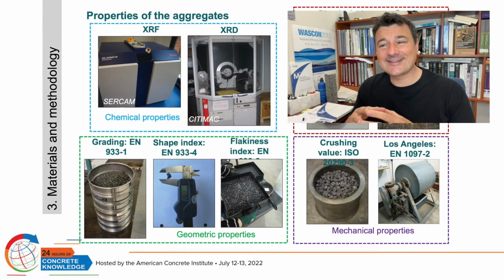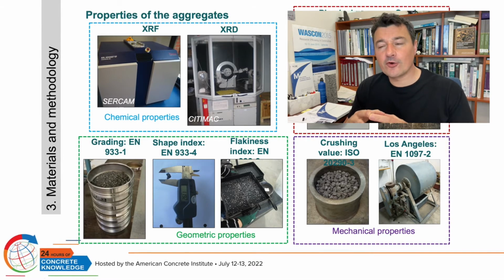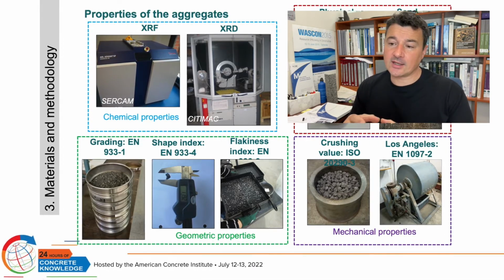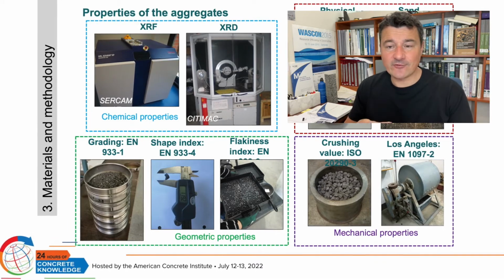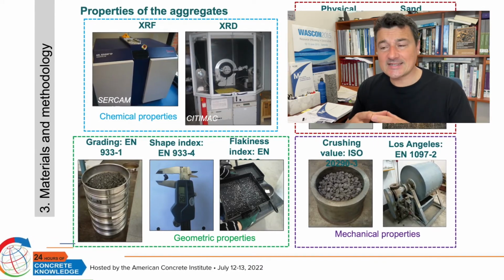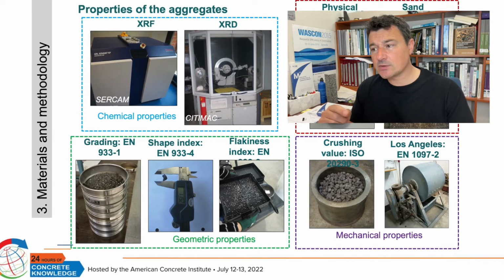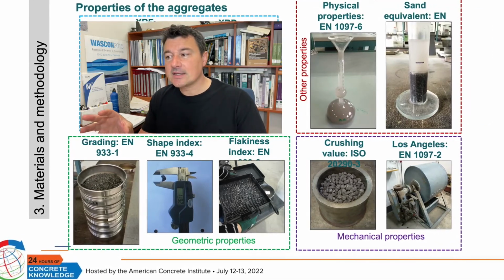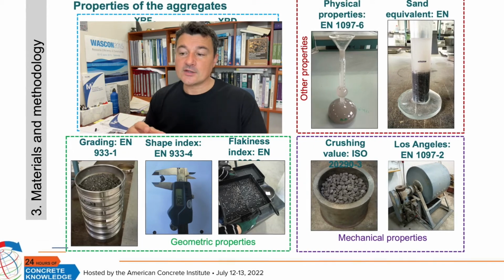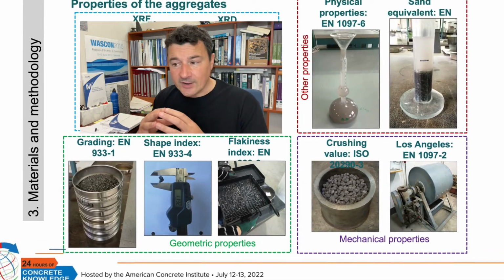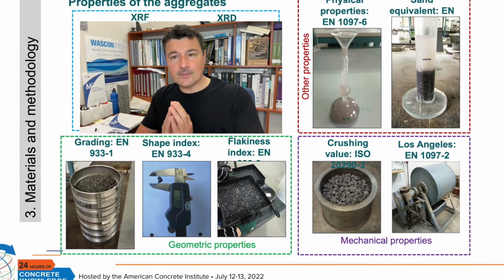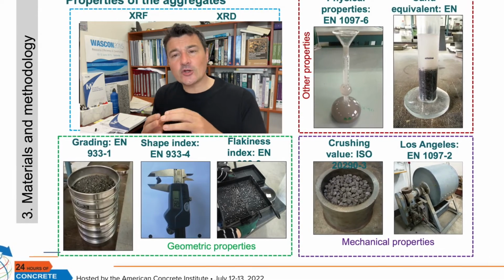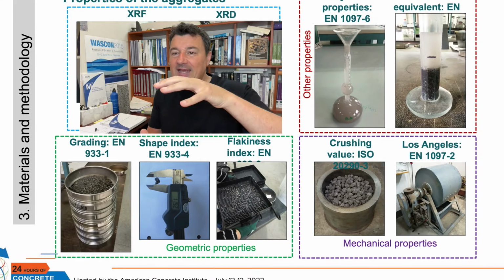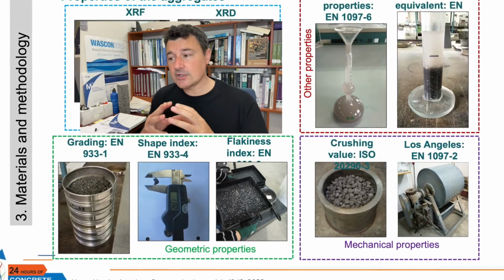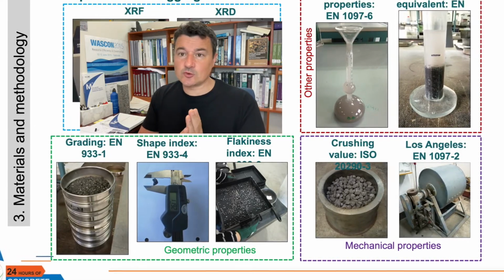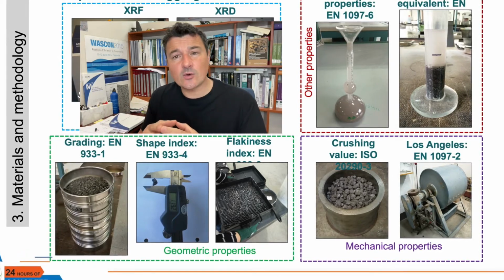In order to characterize the aggregates, we have performed tests for obtaining the chemical composition, X-ray fluorescence. We have obtained the crystalline structure by X-ray diffraction, also the physical properties, the sand equivalent, the grading, the shape index of the material, flakiness index, also the crushing value. This is a very interesting test in order to know the mechanical behavior of the aggregates, and also the Los Angeles test in order to obtain the Los Angeles coefficient.